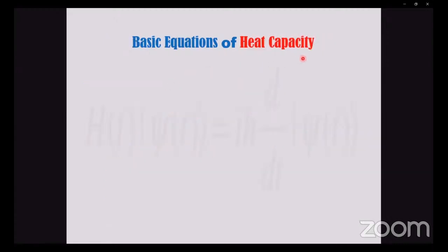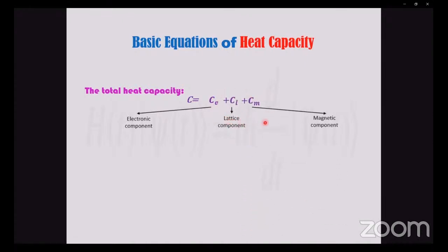The basic equation of heat capacity. The total heat capacity has three terms: the electronic component term, the lattice component term, and the magnetic component. The electronic component is given by this equation, for which the density of states at the Fermi level energy is needed. We obtain it from the WIEN2k code.